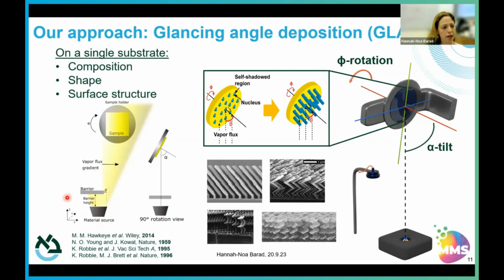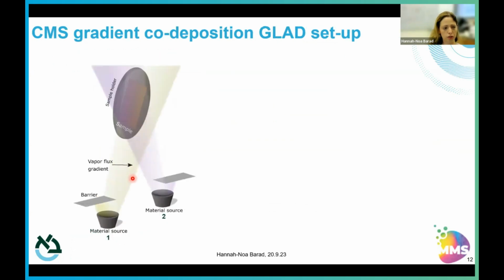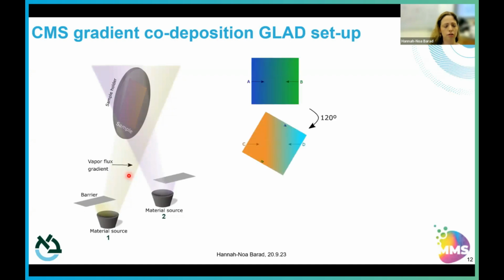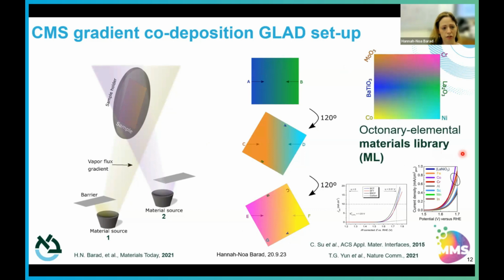And pretty much we put a barrier in front of our source material. There's a dependence on the barrier distancing from the opening of the source and the barrier height, which forms a vapor flux gradient. And this we did by placing two source materials, one across from each other with their own individual barriers placed to form the vapor flux gradient. Then we deposited two materials, rotated by 120 degrees to deposit two more, rotated again to deposit two more, and then we end up with an octonary-elemental materials library.